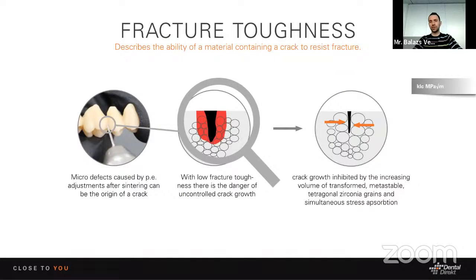Another really important part, comparing, for example, the lithium disilicate materials. In many of the cases, we cannot avoid grinding the zirconia materials after the sintering process. It means every grinding process after the sintering carries the risk that we will get micro cracks, micro defects in the material, and of course it can go through the complete material. So if we are not working with water cooling and proper zirconia grinding tools, we can have a failure really easily and really fast.